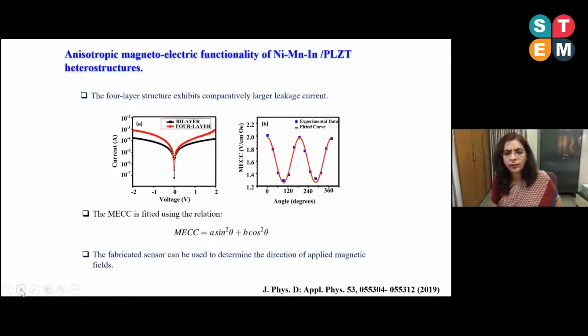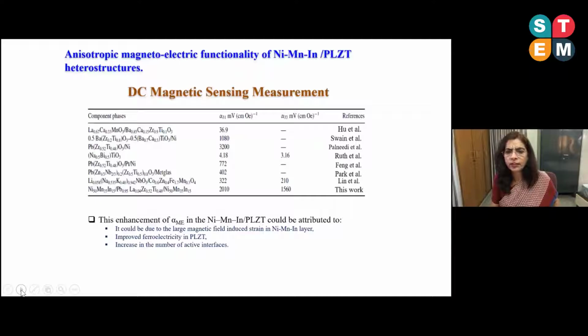This was explained during the leakage current behavior. Then we tried to measure or compare our results with existing literature, and our alpha value comes out to be 2010, while the highest reported value is 3200 in the PZT-nickel case. However, in other cases, our results were quite better and promising.